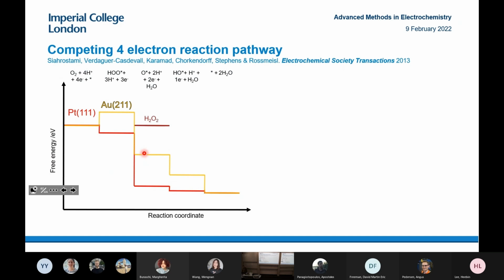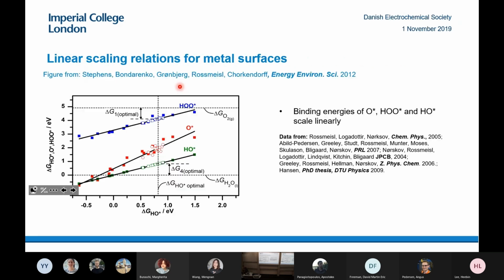So you can imagine, ideally, in the ideal catalyst, you'd have weaker binding to oxygen, weaker binding to OH, and especially to oxygen, if it's weaker than the free energy for making hydrogen peroxide, you'd be able to make hydrogen peroxide selectively. So if this line here was up here. But of course, because of the scaling relations which I already mentioned, it's quite difficult to change the binding energy of intermediates independently of each other.